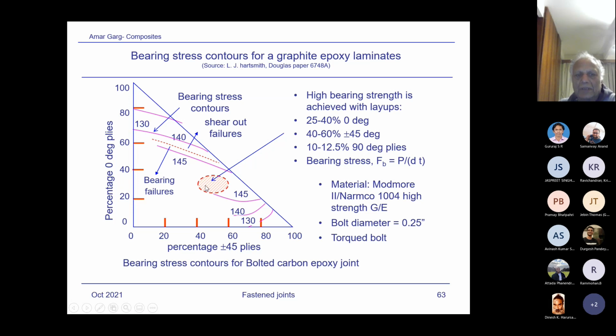So that gives you higher bearing strength allowable in this range, where 45 is around 50%, or 40 to 60%, and zero between 20 and 40%, around 25%. So this gives you the best layup: 25, 40 to 60, and 10 to 12% for 90 plies.